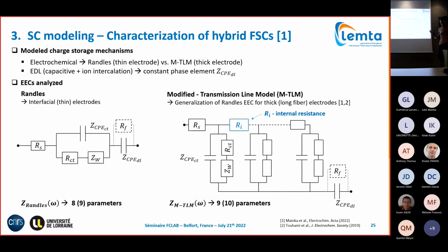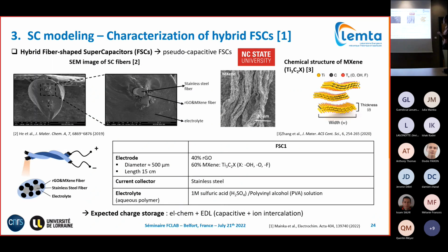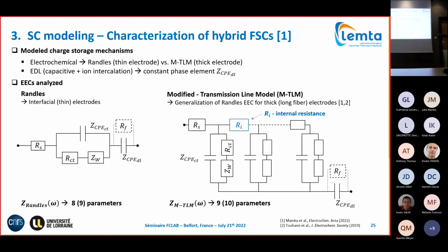Our objective was, so our colleagues developed these devices, and they were interested in our skills to have a model that allows interpreting the experimental data with parameters linked to the physics, in order to have more performant and durable devices. So what we tested were different circuits. What we had to take into account was two contributions to charge storage, one electrochemical, because graphene oxide, MXene primarily, in contact with sulfuric acid is subjected to redox reactions, and you will have charge storage as well. So we tested two different kinds of circuits for electrochemical charge storage.